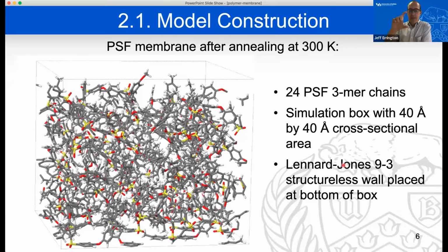During that process, the thickness of the polymer film, so this thickness here, decreased as we decreased the temperature. It became effectively more dense, and the final structure that we got to at 300 Kelvin is the one that you're seeing here. So you can see there's a little bit of roughness in terms of the surface at the top. This is the surface that we're now going to expose to water, as well as graft the polymer tethers onto. So that's the process that we use in order to develop the base membrane that we work with.